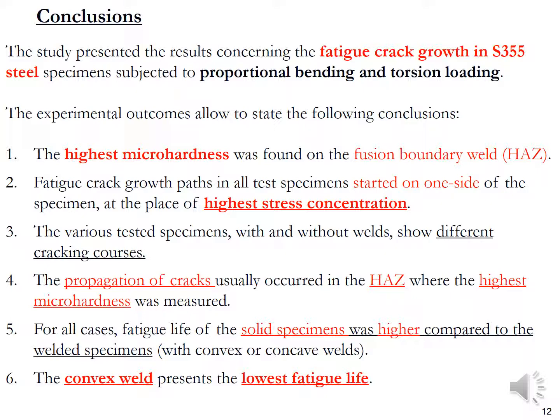Some conclusions: the highest microhardness was found in the heat affected zone. In all cases, the crack starts on one side of the specimen from the weld toe. Different crack paths have been observed. Cracks propagate preferentially inside the heat affected zone where the highest microhardness was found. The shortest fatigue life was recorded for the specimen with the convex weld, while the maximum life was for the solid specimens.